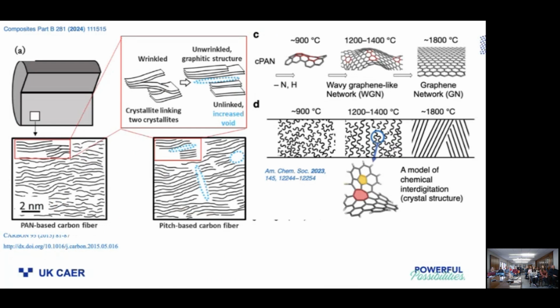Also, these pan-based carbon fibers are not particularly graphitic, the high-strength pan fibers. In fact, this publication describes them as produced in a temperature range of 1200 to 1400 degrees, whereas highly graphitic fibers will see temperatures far over 1800, maybe even over 2500 degrees C. So you're left with a structure described as a wavy graphene-like structure. You have more of an amorphous type structure in the carbon, albeit largely all oriented along the axis of the filament. There isn't long-range order as you would find in a highly crystalline graphitic fiber.